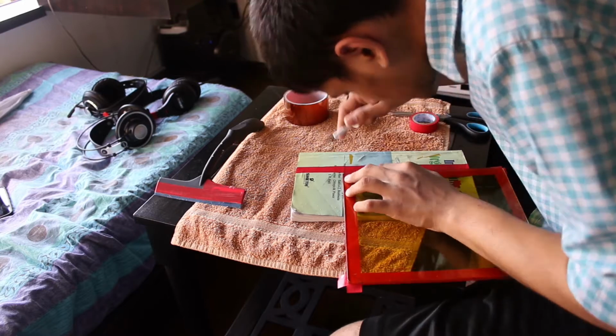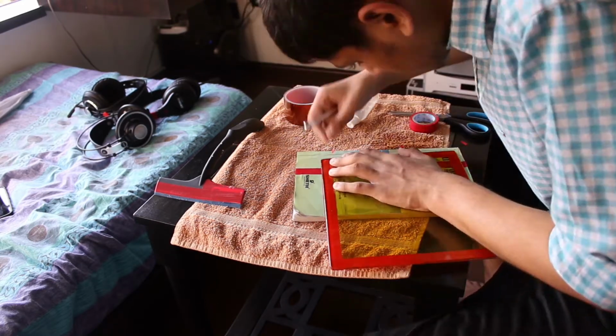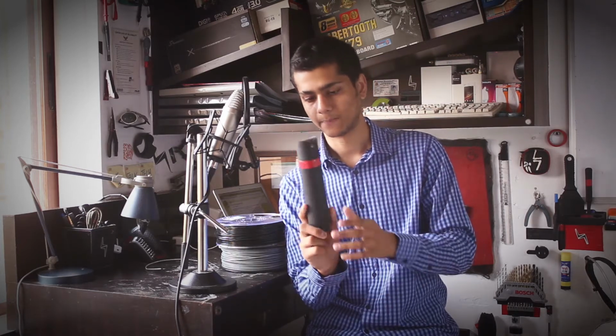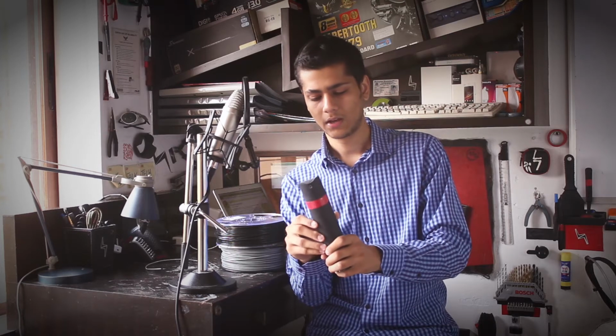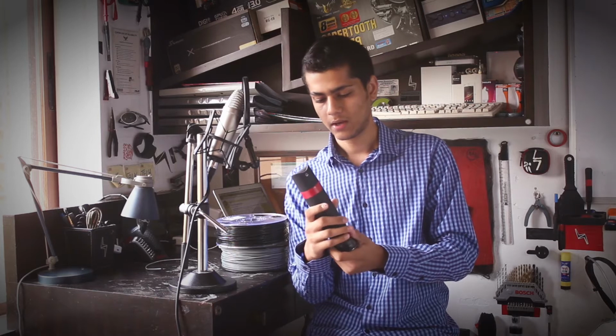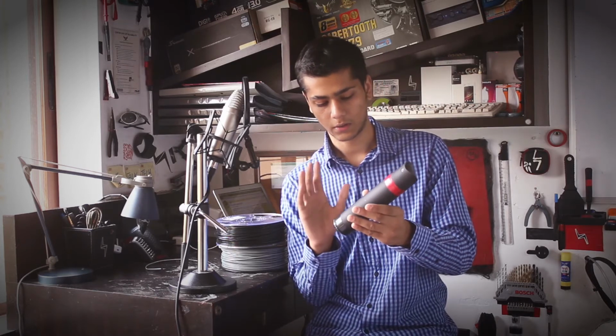Another thing a lot of people suggest while printing in ABS is to use glue stick. I have noticed glue stick has absolutely no impact while printing in ABS. Yes, there'll be some noticeable improvements if you're printing small parts with slight overhangs. Sure, glue stick could work, but in the long run, it just never works. Some people also recommend you use hairspray. I painted it so you cannot see, but this is a normal hairspray you can find in the market. Hairspray does work. I find it to be quite effective compared to glue stick, but again, only with small parts. With big parts, you will not notice any difference. So hairspray is again out of the league in terms of having significant results in solving the shrinkage which ABS has. So I don't use hairspray.